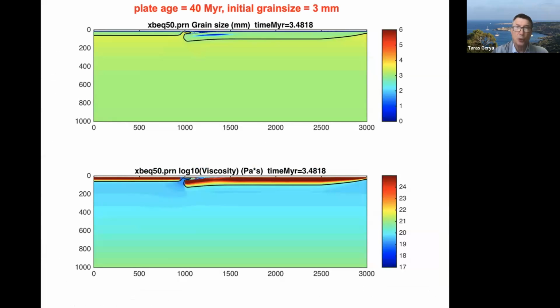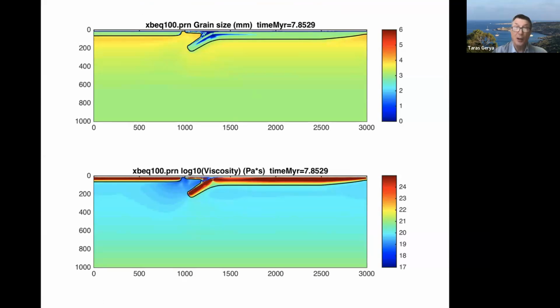Here on this diagram, you see on the top diagram the development of the grain size. Blue means very low grain size. And then you immediately see that during the subduction initiation, some initial bending of the slab starts to happen. Then exactly near the region of the brittle-ductile transition, we see this blue cloud, which implies strong reduction of the grain size. And it's not surprising, because there we have very high stresses, since material is still quite rigid and of high viscosity, and it's subjected to bending stresses. On the other hand, deformation is also significant. So we need some 10% of deformation to accommodate this bending. Here we see the viscosity picture, and not surprisingly, viscosity is somewhat reduced on the top of the plate where we have brittle deformation, effective viscosity, and in the bottom of the plate where we see this grain size reduction.